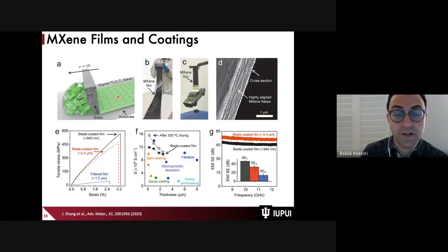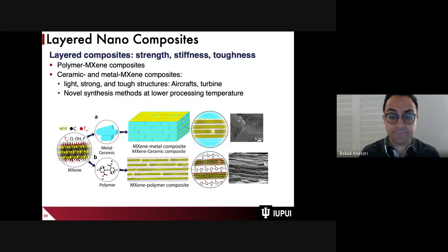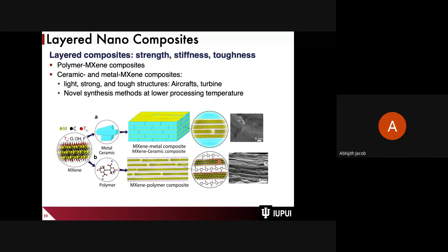And these are not really sophisticated production. We have the MXene, and they just use a blade to flatten it to make these films. They have very high conductivity, up to 15,000 Siemens per centimeter, and they outperform many materials in electromagnetic interference shielding that I mentioned earlier.